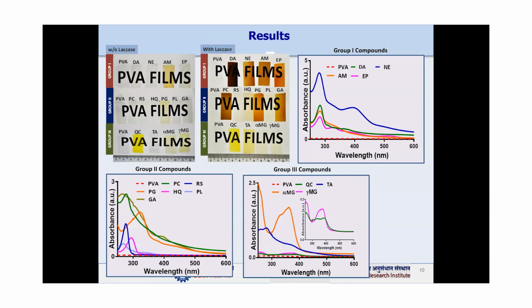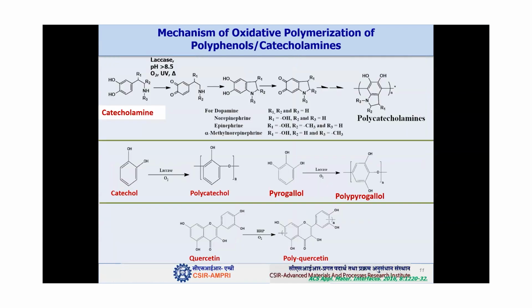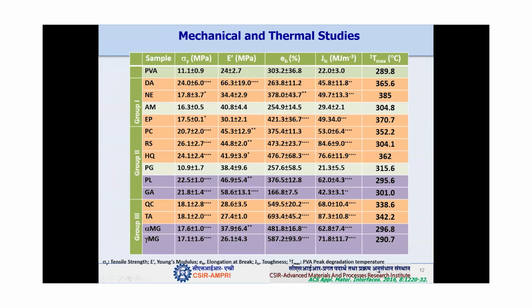So to confirm the polymerization, we have done UV visible analysis, because usually polymers give peaks in the visible region. So we have actually seen the rise of these peaks in the films where the compounds got polymerized. So I'm not going into detail, but this is one of the techniques by which we confirm the polymerization of the compound. So this is the mechanism by which these compounds can be polymerized. So this is for the catecholamines, then this is for the catechol, then pyrogallol, how it polymerized, then the quercetin, how it polymerized. So this is just a brief mechanism about how they are doing things.